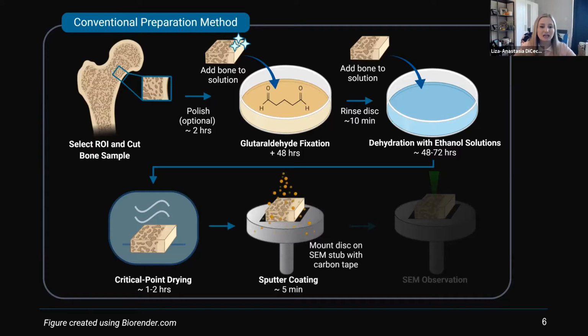And this is a pretty standard process in most EM prep methods. But for bone, especially if it's not embedded, it may be porous, and the sputter coating process is more or less a line of sight process. So you could have pores that are completely not sputter coated or not well coated, which can affect overall the quality of your imaging.